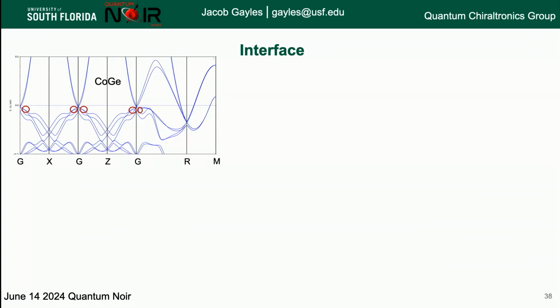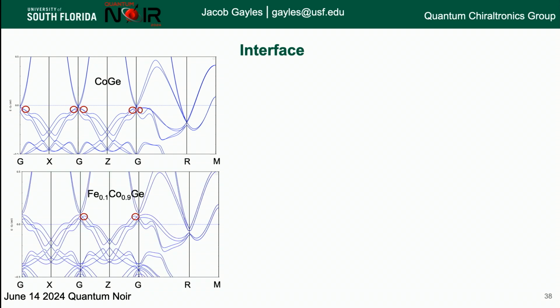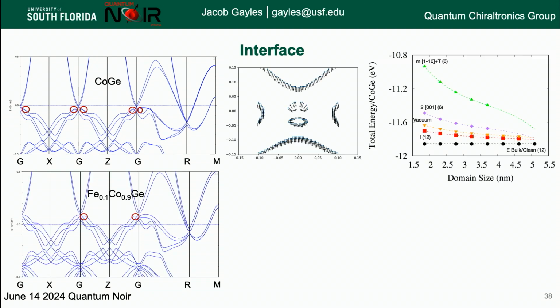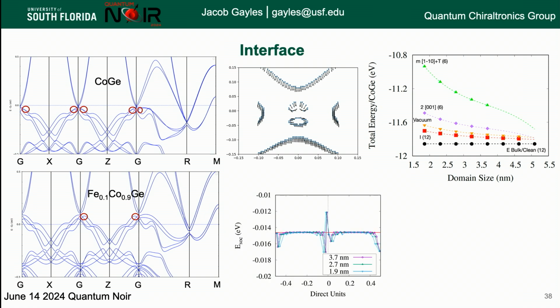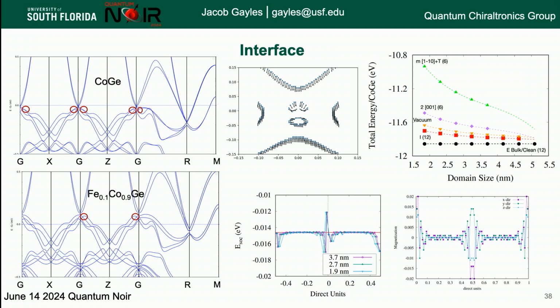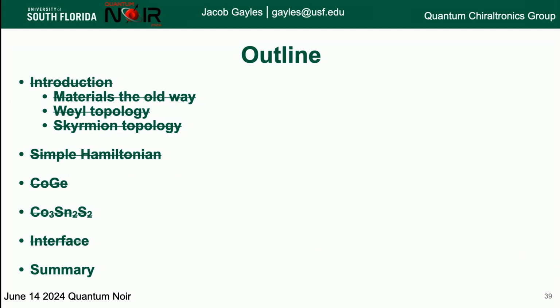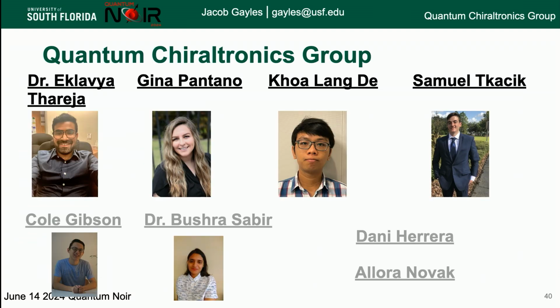Good. That's it. Oh, well, I'll skip this slide, but this was just proving, all pen and paper theory, that we can actually do it in these iron, cobalt, germanium materials, which are magnetic. It shows the stability of these materials in terms of energy, and also shows that we can change the amount of spin-orbit coupling at the interface and the magnetization of these materials at the interface. Good. That's my group.